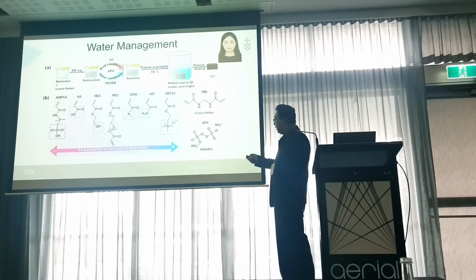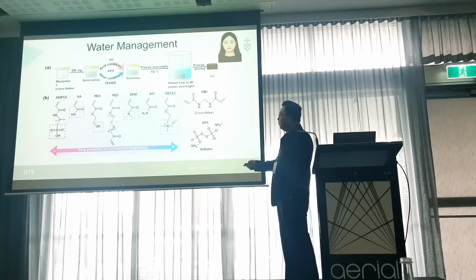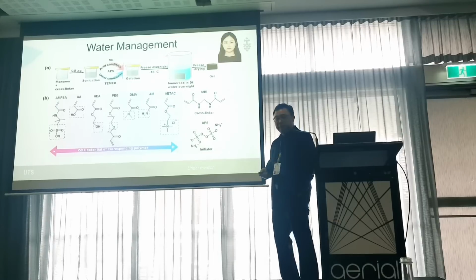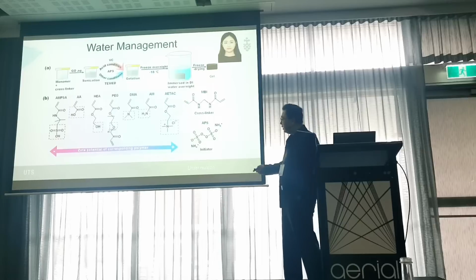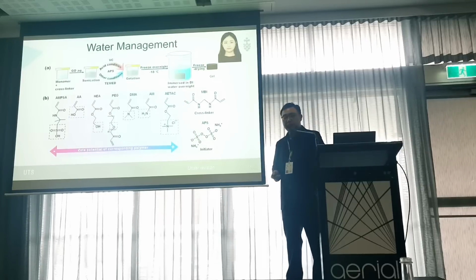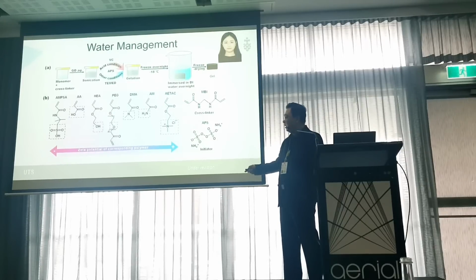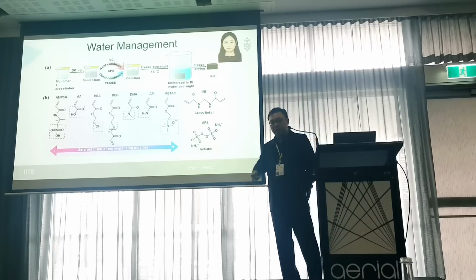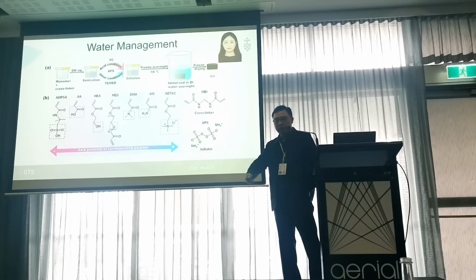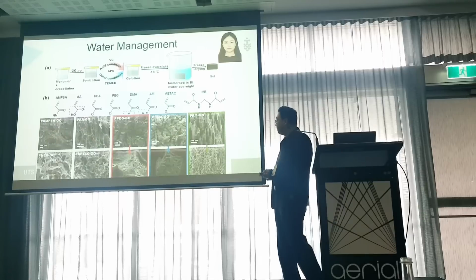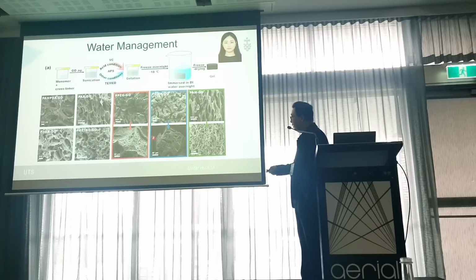So in this study, I asked Shudi to prepare a series of hydrogels. We use the same 0.1 weight % of graphene oxide as the photothermal material, all the same. But we try different polymer precursors, as you can see, from the negatively charged sulfonic acid group to the positively charged ammonium group, with this kind of neutral ether group or hydroxyl group. Using the same method, we crosslink them and freeze them to prepare hydrogels. As you can see, all the hydrogels have the micropore structure.